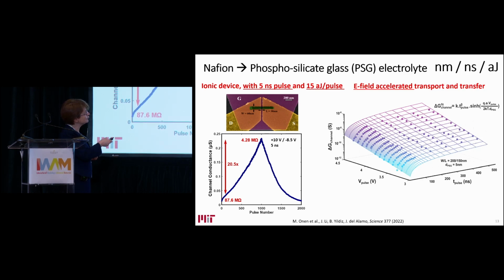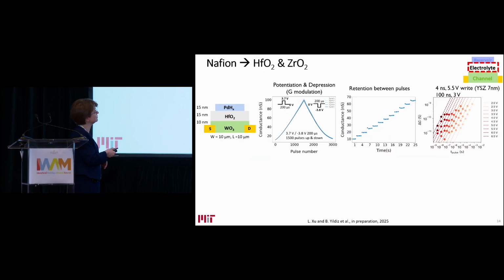And if you look at changing conductance as a function of programming voltage and programming time, we see a hyperbolic sine dependence on the field across the electrolyte. So we are dealing with, in this geometry, field-accelerated proton transport through the electrolyte. If you go to much thinner or better electrolytes, we can run into the same behavior for field-accelerated charge transfer reactions or redox reactions. And we will come back to this also.